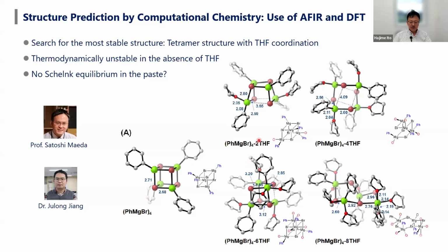They finally found that this cubic-like structure is the most stable for the Grignard reagent prepared by ball milling reaction conditions. Interestingly, coordination of THF is very important to stabilize this new Grignard reagent.